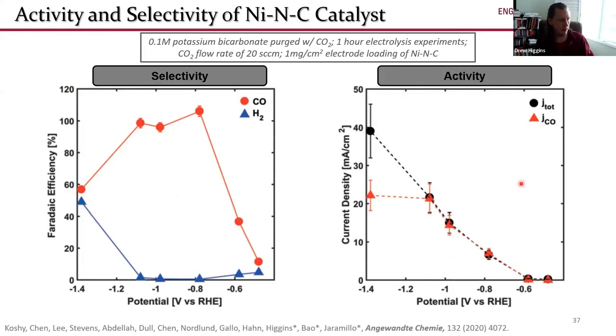So what we found is that under the range of electrochemical potentials that were investigated, for example, between minus 0.7 volts versus the RHE and minus 1.1 volts versus the RHE, these catalysts were very selective towards pretty much exclusively carbon monoxide. So we had selectivities that were right around 100%. So this catalyst exclusively was producing carbon monoxide. But then as we started to go lower in electrochemical potential, they started to produce a little bit more hydrogen. So we found this kind of as our sweet spot of where this catalyst could be very selective for converting CO2 into carbon monoxide.